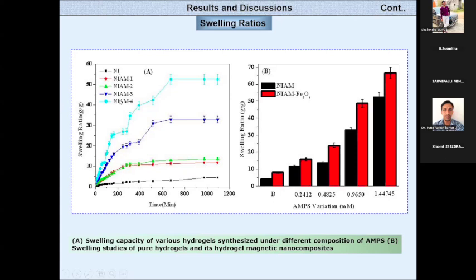So wherever AMPS polymer is there, you are getting a very big swelling ratio. It means per each gram it is taking almost 100% of water. Then we have selected only one type of nanoparticles. There also we have studied the swelling study for magnetic nanoparticles. Here also you are seeing some superior nature. So if you are taking a hydrophilic polymer as well as nanoparticles inside of the hydrogel network, that will give the high swelling nature.